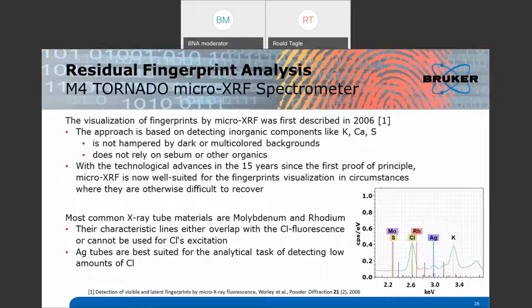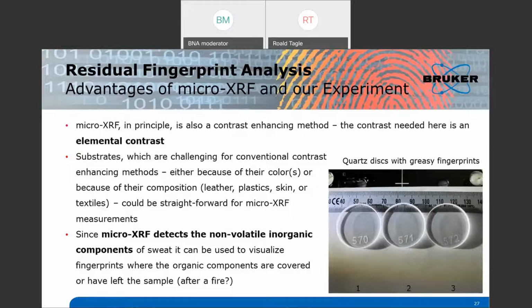We addressed this in a webinar on concrete, where chlorine is usually an element of interest, and therefore we already showed some differences between those two anode materials. And what we did: first, micro-XRF is also a contrast enhancing method. Here we need an elemental contrast. So if there's an element in the fingerprint which is not in the substrate, we get high contrast. And if the element is also in the substrate, then the contrast gets less.